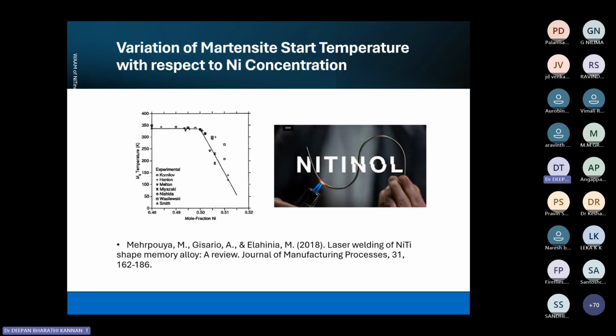Coming to the challenges, specifically with respect to nitinol shape memory alloy, a small change in the chemical composition will have a very large negative effect on the phase transformation temperature. If you remember from the beginning slides, I told you that the shape memory effect mainly depends upon the four transformation temperatures: austenite start, austenite finish, martensite start, and martensite finish. So during wire arc additive manufacturing, if the heat input is not selected properly, it may change the chemical composition, and we may not get the wall with our required austenite finish temperature, because only on reaching the austenite finish temperature will the wall return to its original shape.